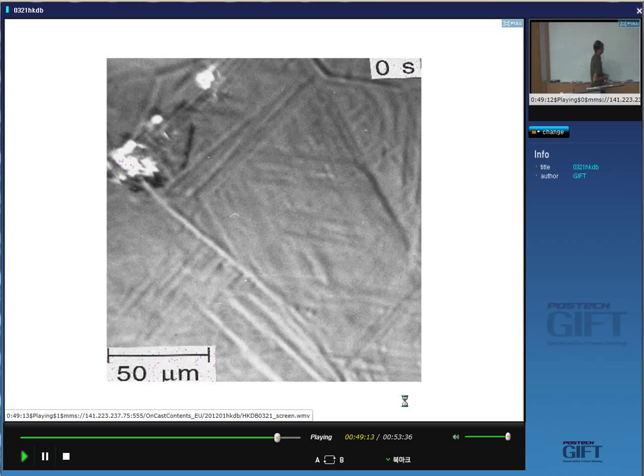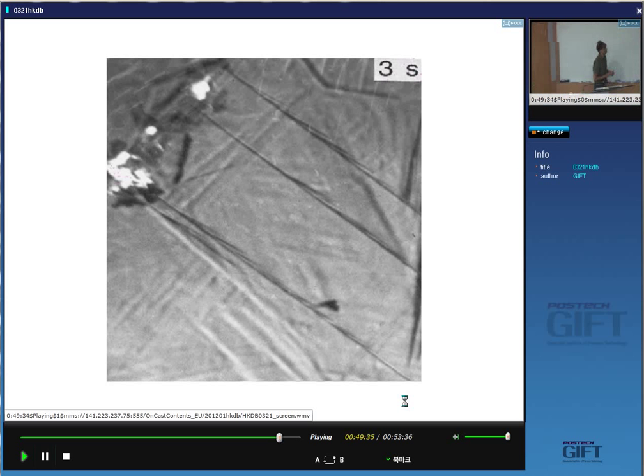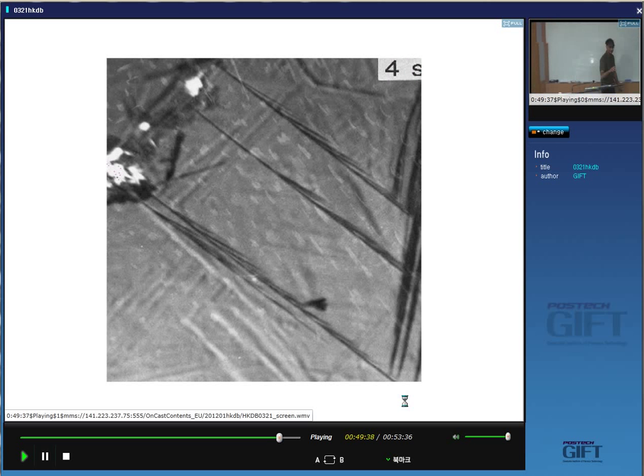I'm going to show you a sequence of four pictures from a photoemission electron microscope, and you'll see individual platelets of bainite growing. Here, can you see these ones? Yes, those are individual platelets of bainite. By looking at these images, we can measure the growth rate, and it's about 3 orders of magnitude faster than would be permitted if we allowed carbon to diffuse during transformation.